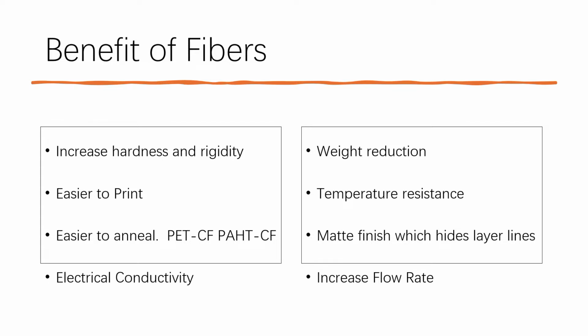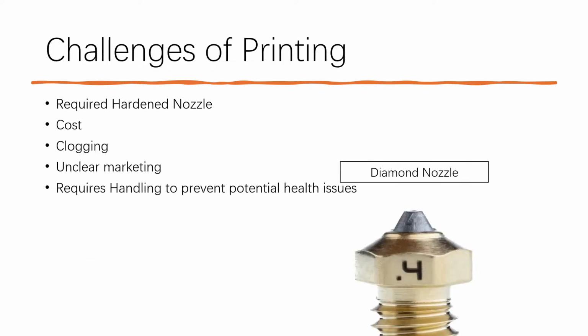And there are actually two very interesting things we found. When using powderized carbon fiber, it makes the skin, the surface of the print, have a matte finish. It looks a lot nicer. And also one very surprising thing is that some of the carbon fibers can increase the flow rate. It's counterintuitive, but we believe that's because you don't have to melt the carbon fiber, and it also has better heat conductivity, so it helps the plastic melt. And we noticed that in some of our filaments.